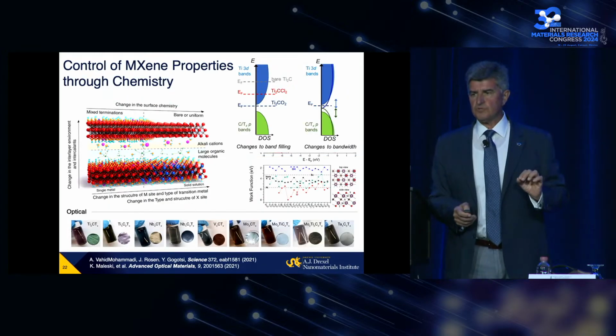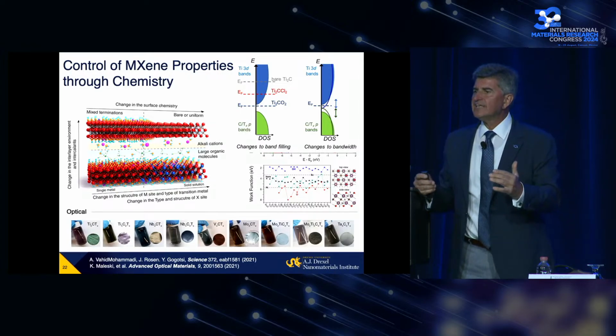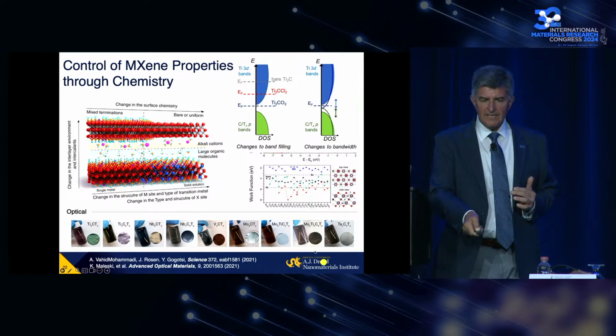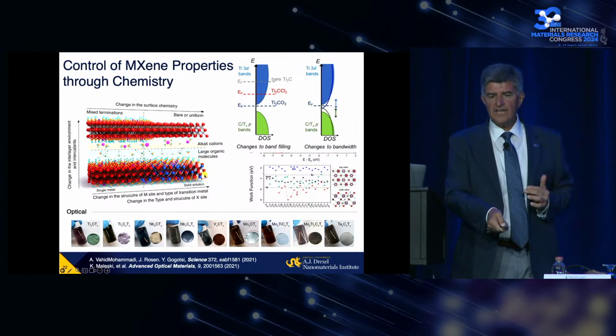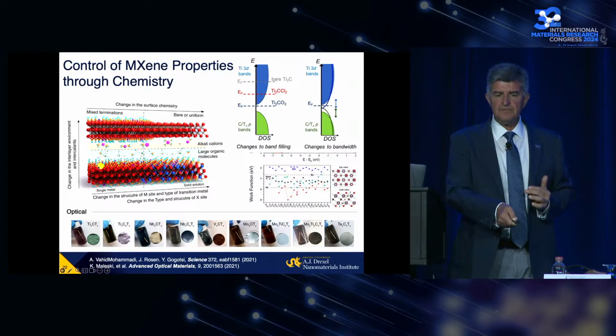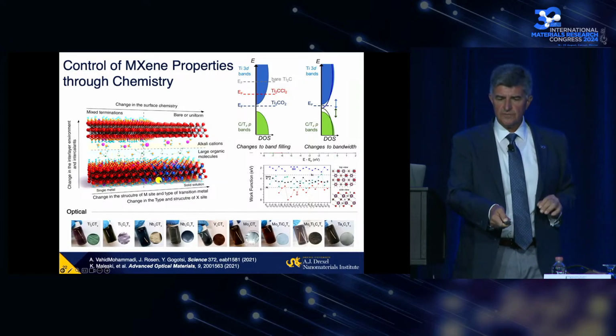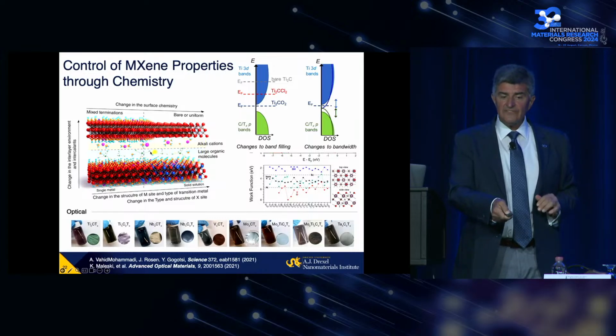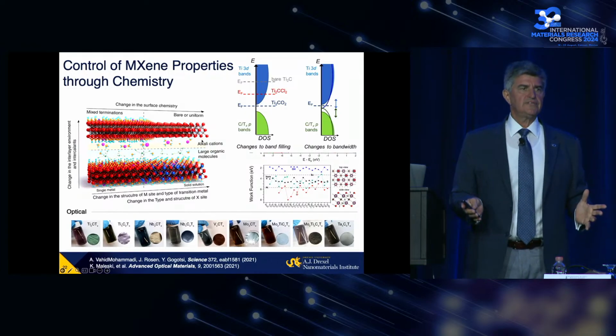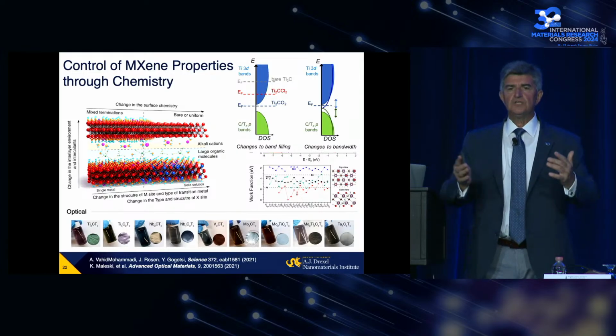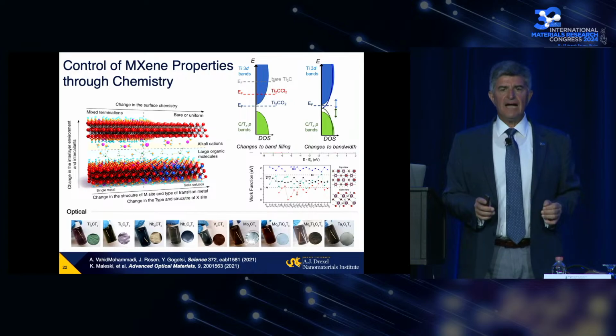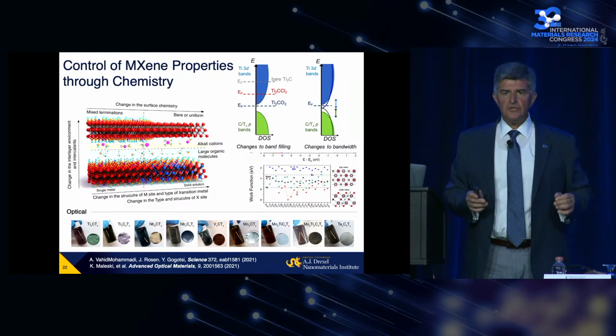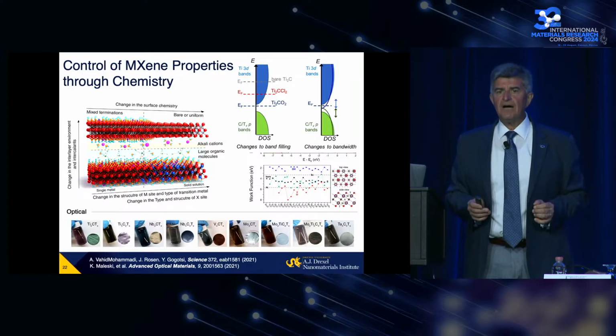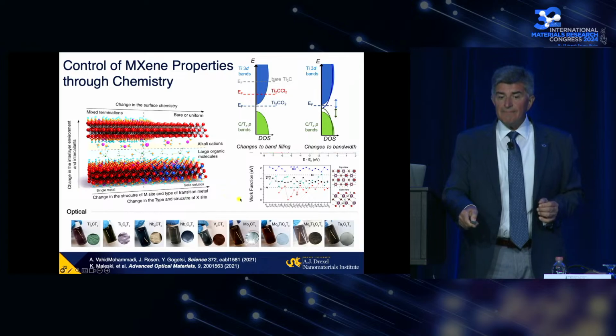But what is most important? When we have this variety of materials, we can tune those properties. We can control them by selecting the metal, carbon, nitrogen, oxygen. We can change the surface termination, number of layers, arrangement of layers - remember out-of-plane, in-plane ordered structures. We can also graft organic molecules onto the surface, and we can intercalate ions. So we can tune materials to get what we need for application, not take a single material as given by nature, God, or your colleague at another university, but design them as you want. There are many interesting things happening.